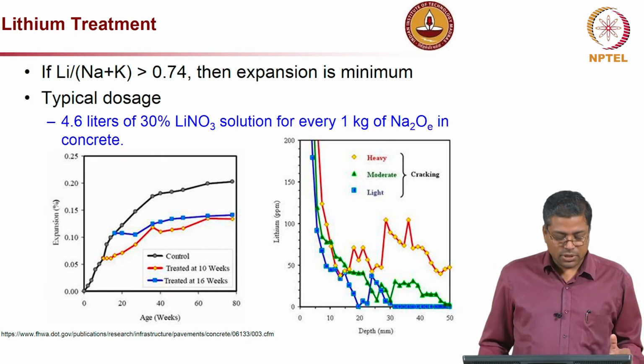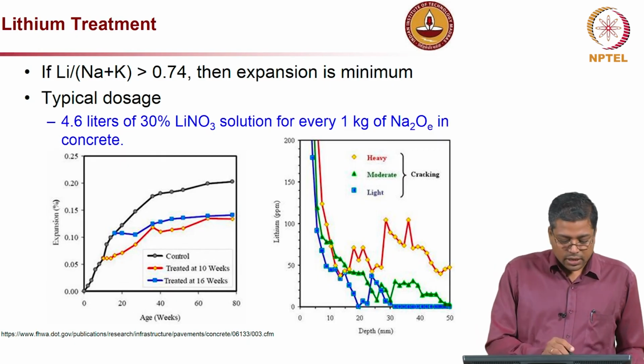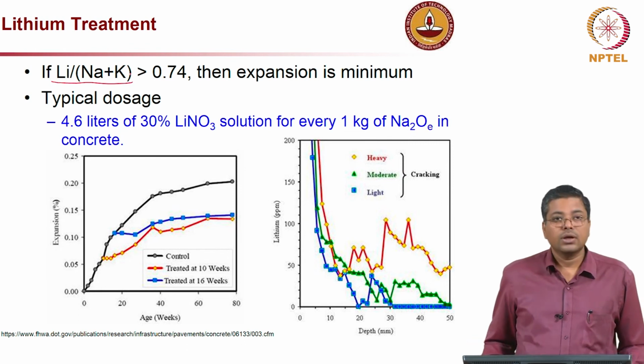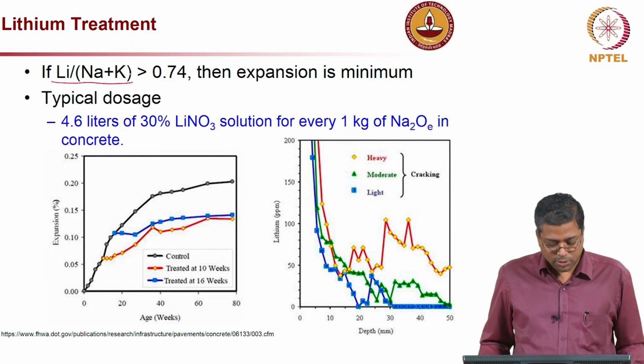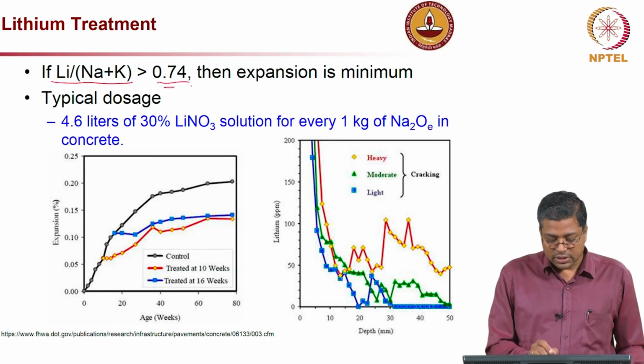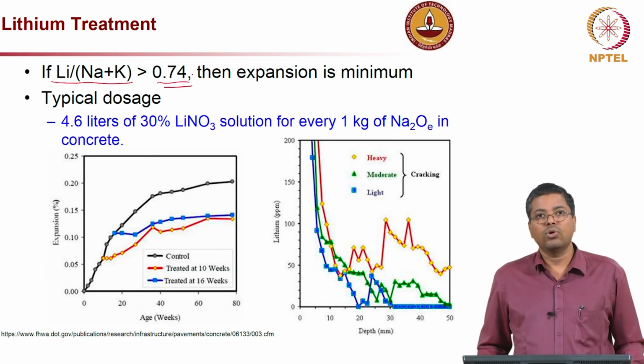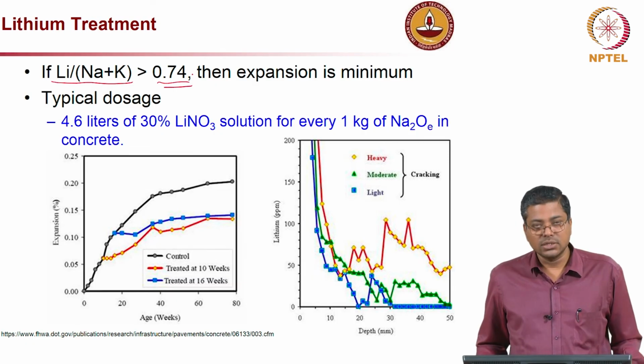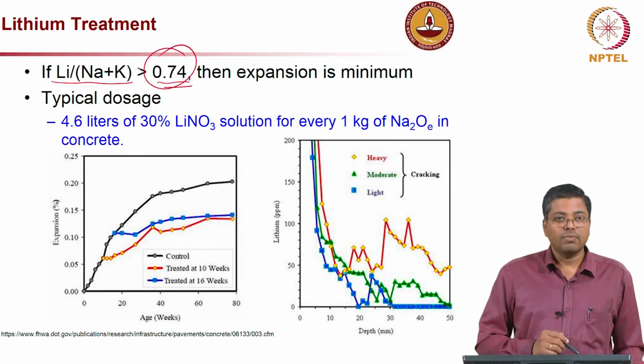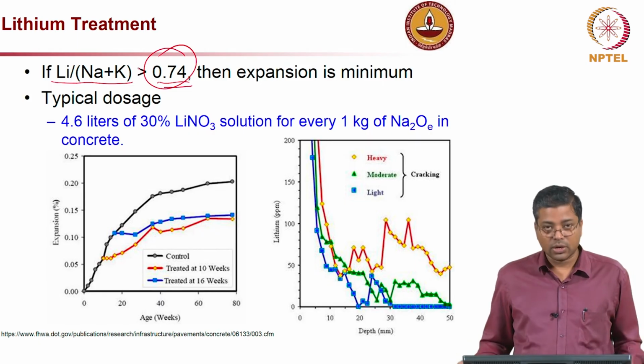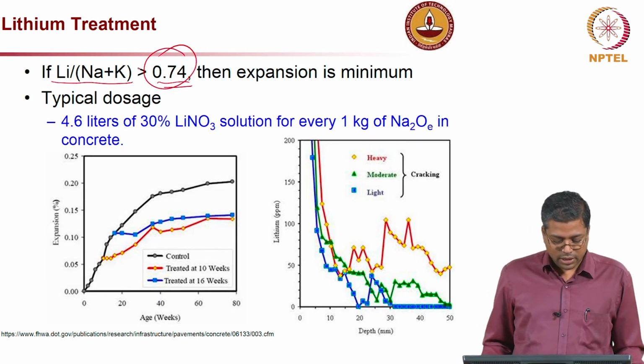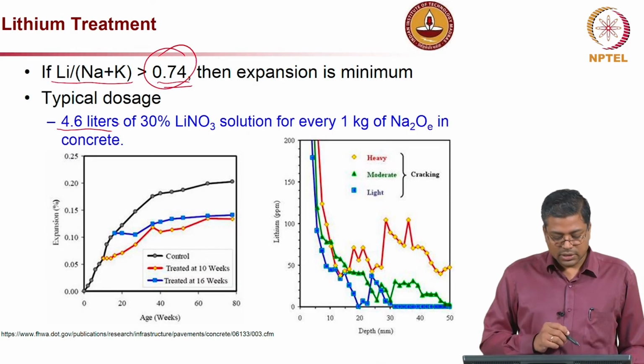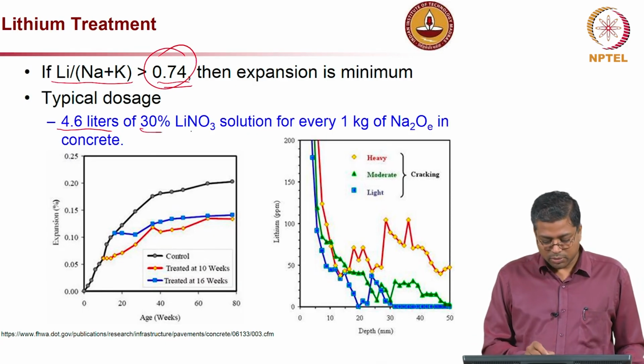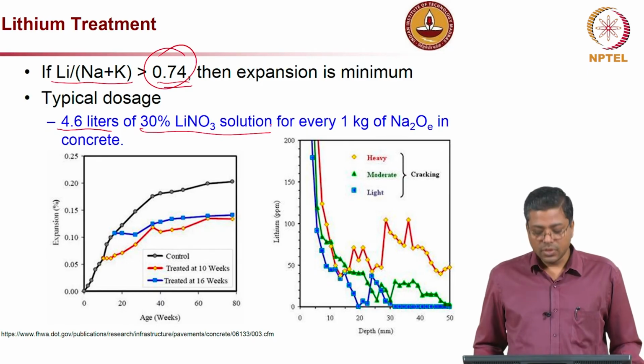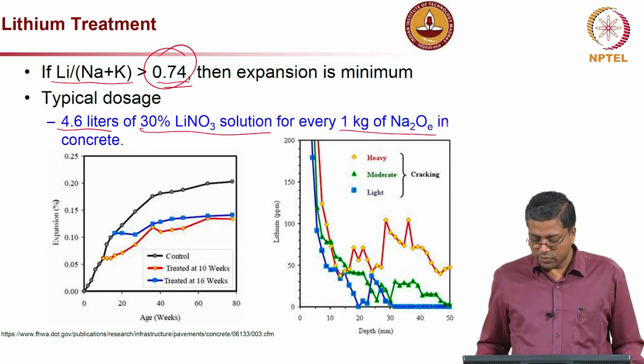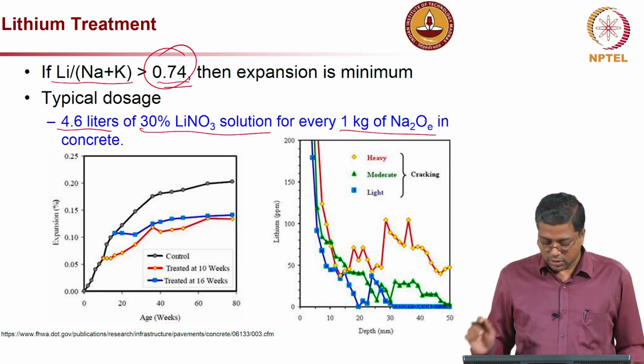Now, what is the idea behind this lithium treatment? If the ratio of lithium to sodium plus potassium concentration is greater than 0.74, then we say the expansion is minimum. So, this is the typical ratio requirement, how much lithium is to be impregnated. The typical dosage is about 4.6 liters of 30% lithium nitrate solution for every 1 kg of sodium oxide equivalent in concrete.